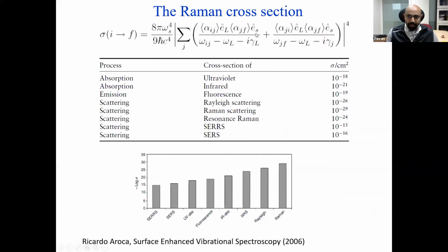I would not go into the details of the Raman cross-section, except to mention that the Stokes frequency scales as the fourth power, which means that it goes as inverse to the wavelength to the fourth power. And it is also connected to something called a resonant Raman process, where if you have an eigenstate which matches with the excitation laser, omega L is the frequency of the laser, and omega ij happens to be the eigenstate in that particular molecule. If they match with each other, then you end up getting a very large resonance. And this resonance can be further utilized for various interesting optical processes.